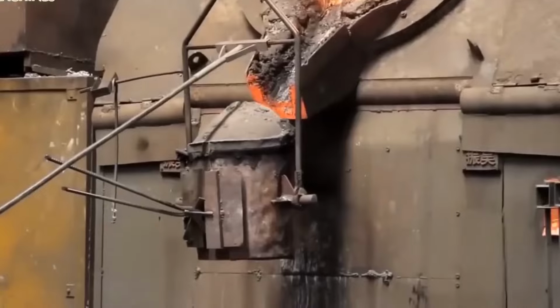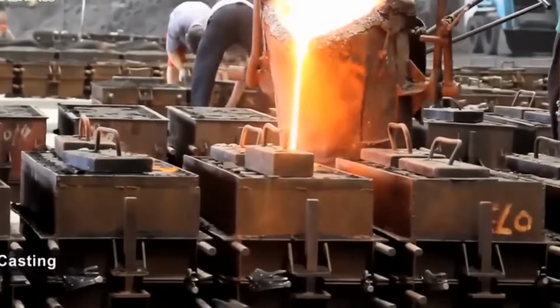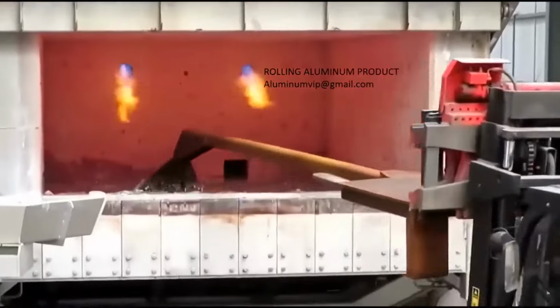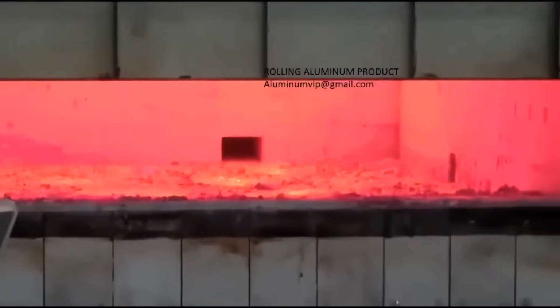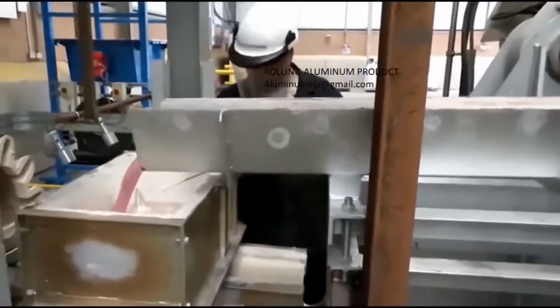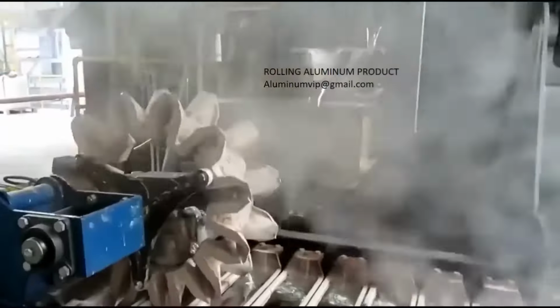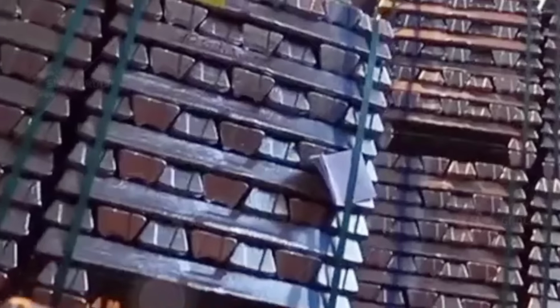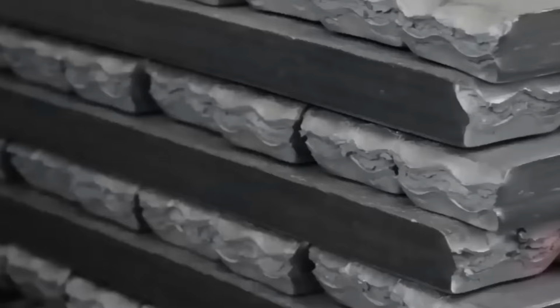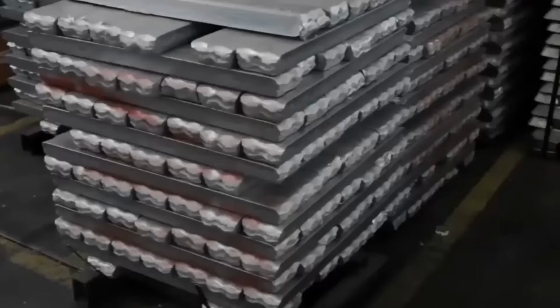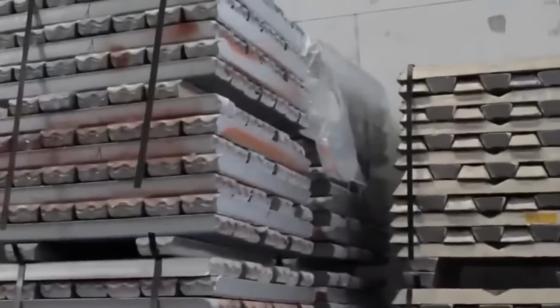casting. Once purified, the glowing liquid metal is poured into molds to cool and harden. One widely used method is direct chill casting, where water sprays directly onto the metal as it leaves the mold, cooling it quickly and preventing cracks or defects from forming. The result? Massive ingots that can weigh up to 27 tons each and measure 10 meters long. It's astonishing to think that each of these giant blocks contains the recycled aluminum from roughly 1.5 million cans.